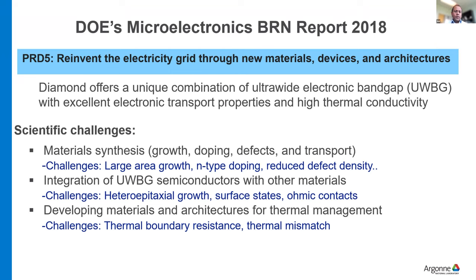But there are several challenges for the heterointerface growth, because it's very difficult to grow diamond on other substrates. Of course, the interaction of the surface states, the contacts to the diamond. And then, when we talk about integration, there are also other aspects of thermal management, where, when you try to integrate this material with other semiconductor materials, even though the thermal properties are excellent, you have to think about the thermal boundary resistance, thermal expansion coefficient mismatch, and so on.